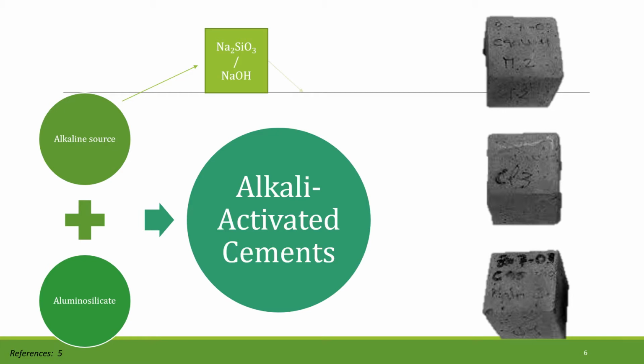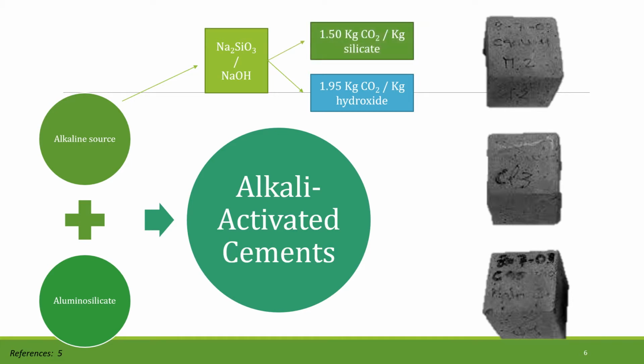However, its manufacture requires high temperatures, and approximately 1.95 kilograms of carbon dioxide are emitted per kilogram of hydroxide and 1.50 kilograms of carbon dioxide per kilogram of silicate. Therefore, the search for alternative activators with less environmental impact arises, so this work presents the reuse of industrial glass waste as a raw material in obtaining an alkaline activator.